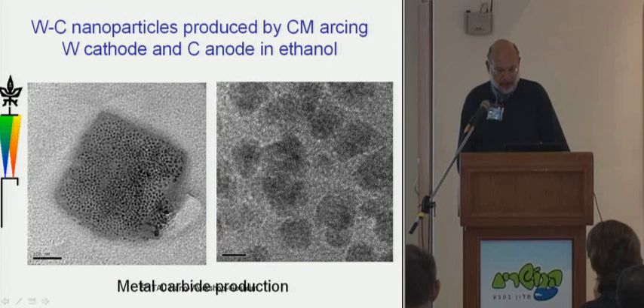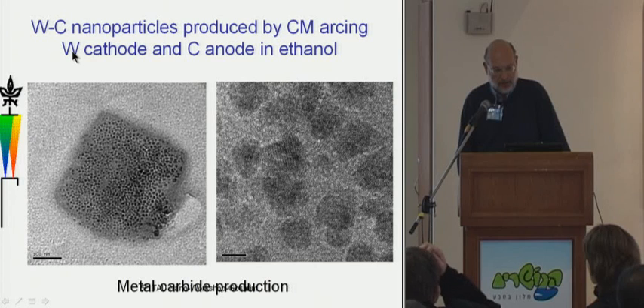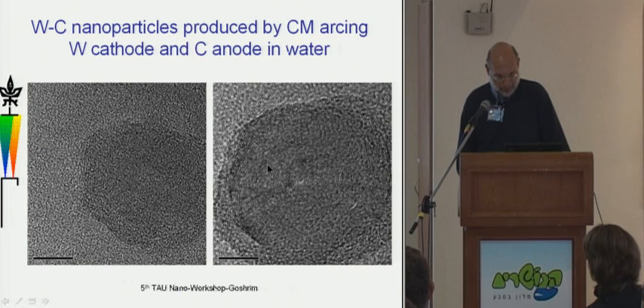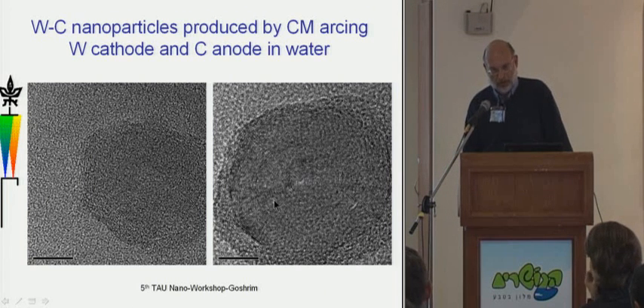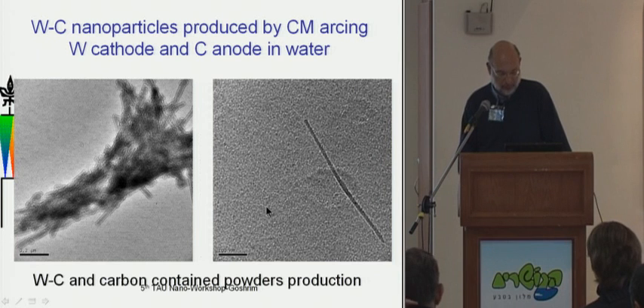This is a composite of some compound of, I won't call it tungsten carbide, it's not stoichiometric, but some combination of tungsten and carbon produced by arcing a tungsten cathode with a carbon anode in ethanol. And these also produce a sort of nano onion, or if you will, fullerene within a fullerene kind of arrangement. These are not graphitic, but rather the characteristic separation is that of tungsten carbide. I think here you can see very definitely this kind of spherical structure.